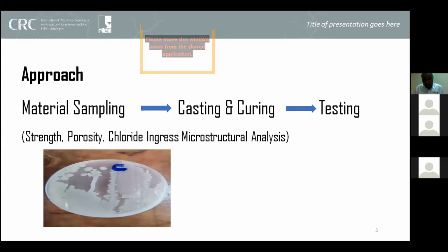The approach I took in the study focused on using the newly developed limestone calcined clay cement, and also the commercial Portland cement as the control cement. Mortar prisms were made using both, using limestone calcined clay cement at a water to cement ratio of 0.5.